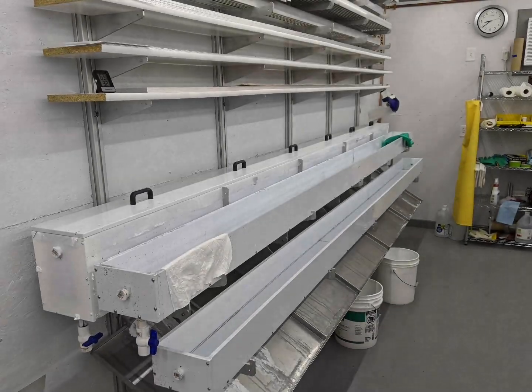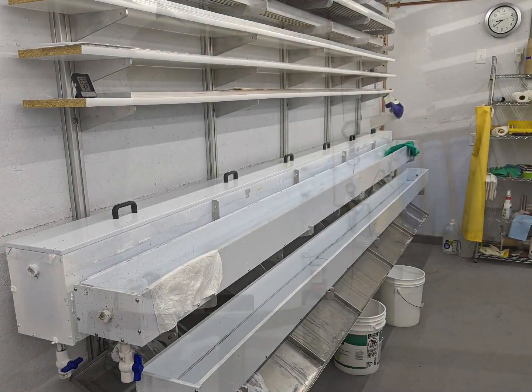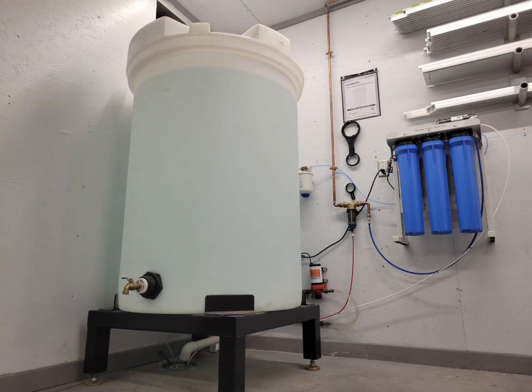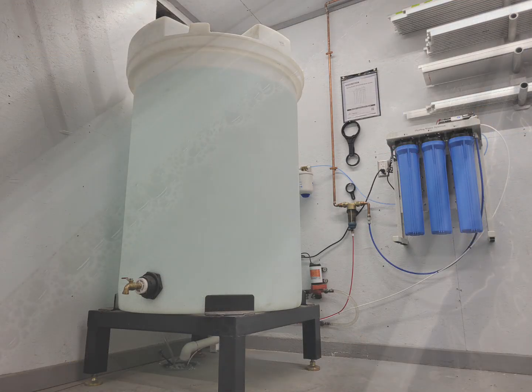The etching process is absolutely critical to achieving a good, strong bond with the adhesive. We monitor the composition of the etching bath very closely, as well as keeping a large supply of fresh RO rinse water for post-etching cleaning. After the etching process, the aluminum will begin to oxidize right away as soon as it's exposed to the air, so we immediately perform a thorough forced dry of the components and directly move on to the adhesive application.